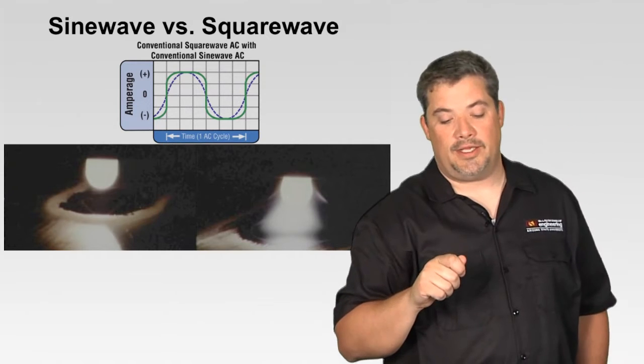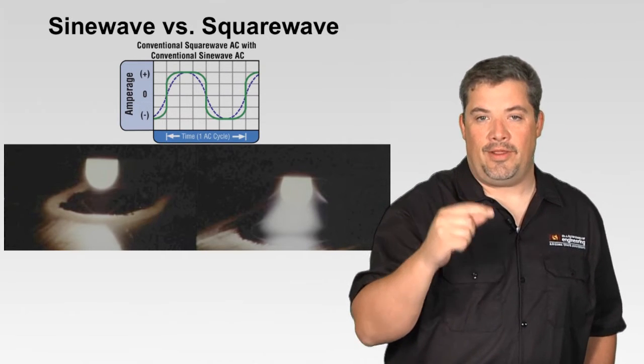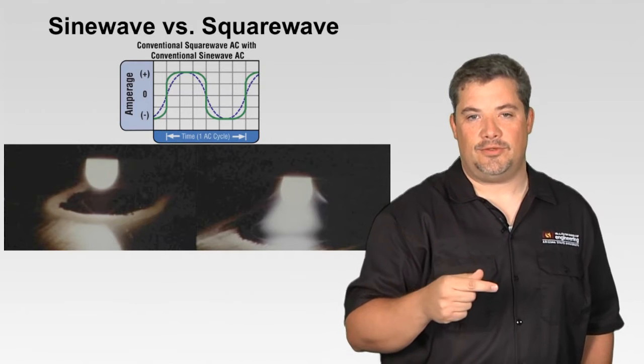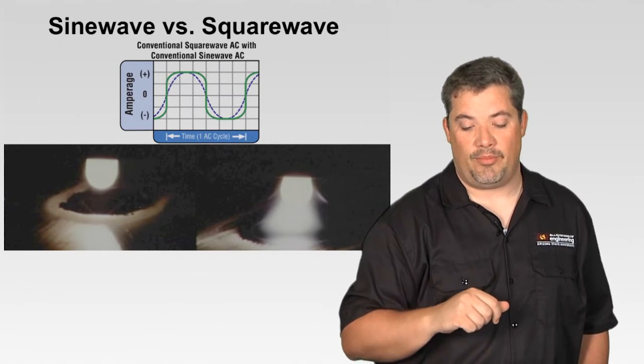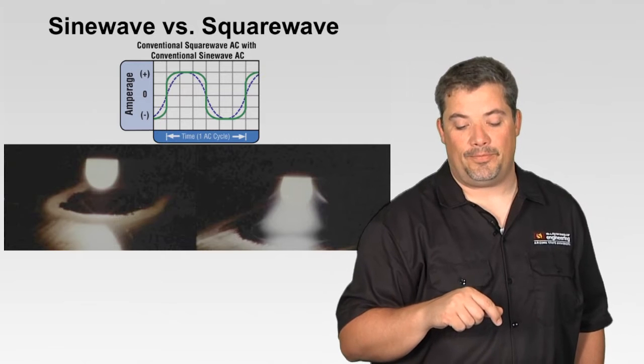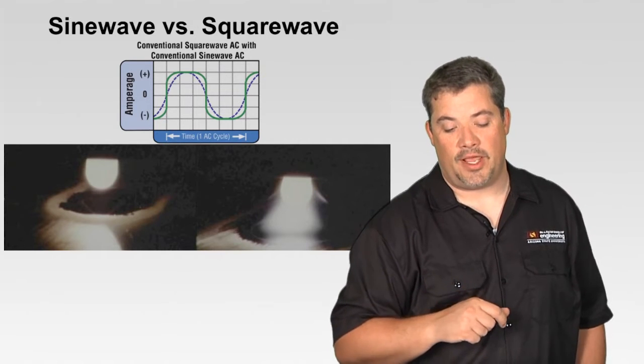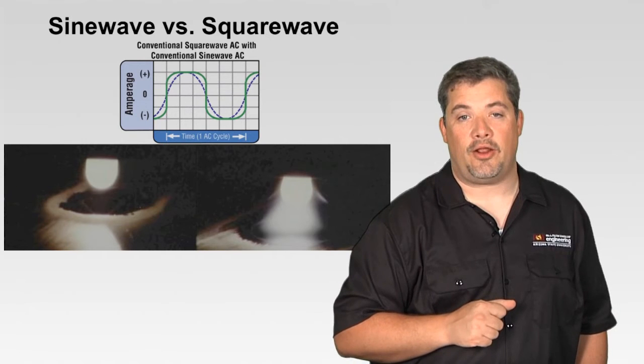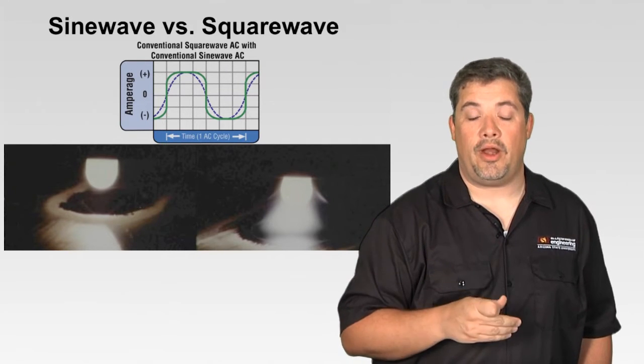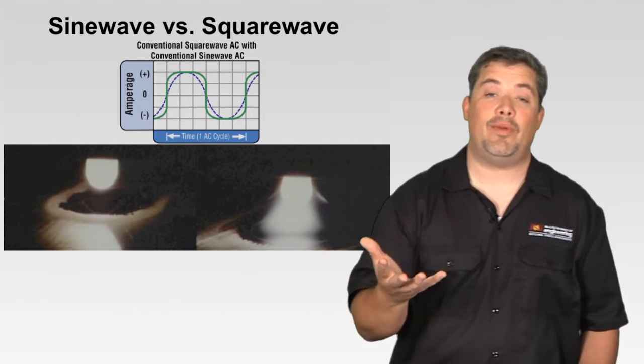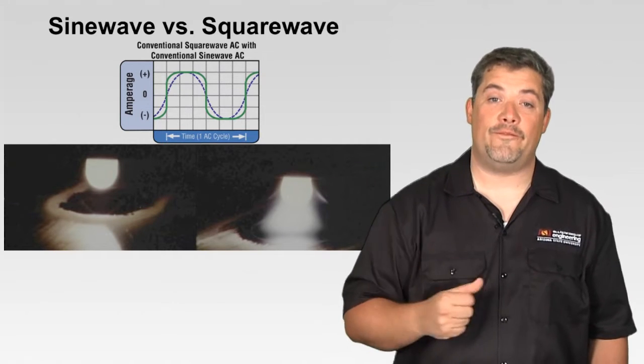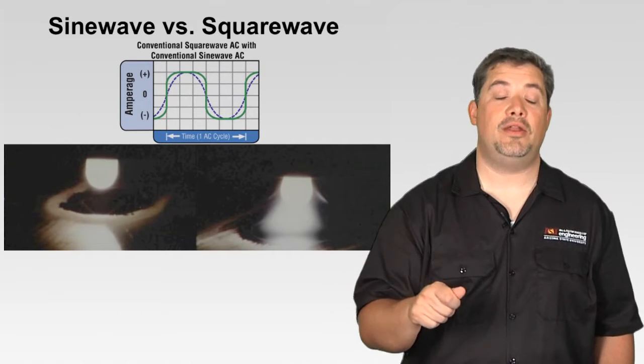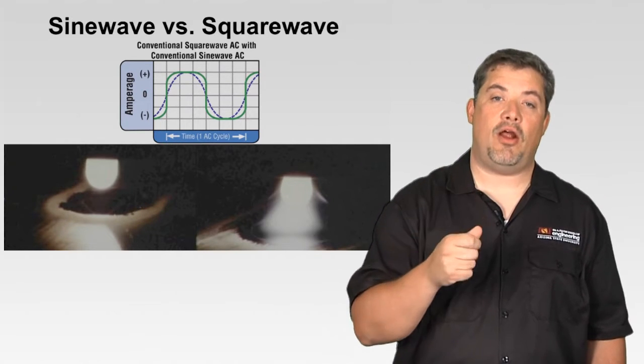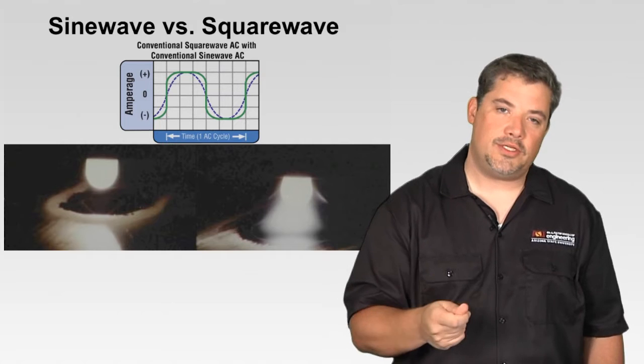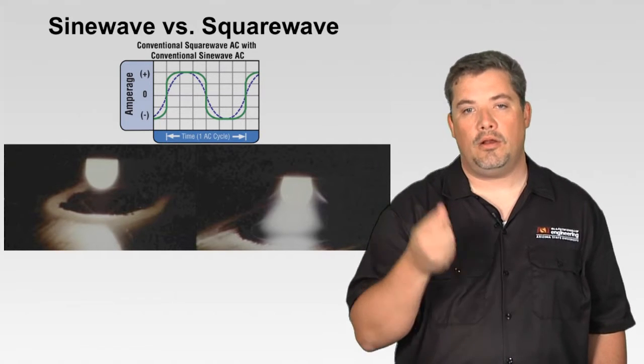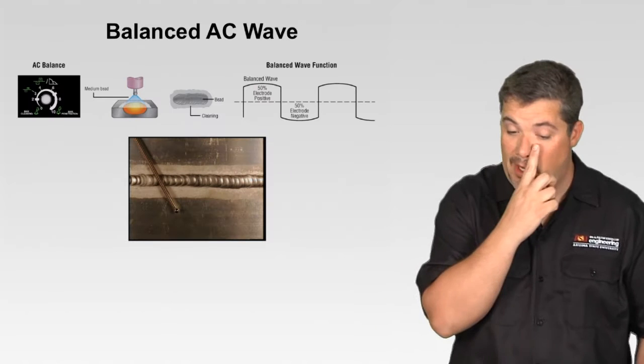For you calculus guys and gals out there, this is where area under the curve comes into play. The green line is our square wave AC shape, and the blue dotted line is our sinusoidal conventional AC wave shape. You can see there are two different areas under that curve, and the one with more area is putting more energy into my part. It's letting me weld more efficiently. So the square wave was monumental in AC TIG welding. It made that arc so much more stable, with more energy there. I could weld better, longer, and just make more money.